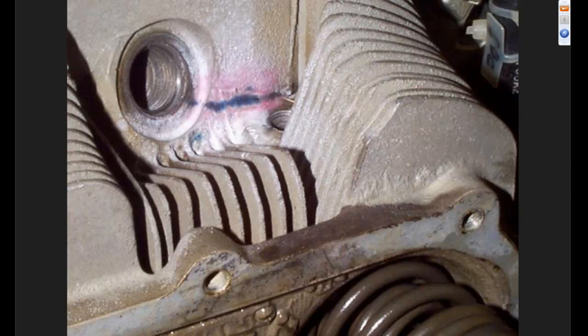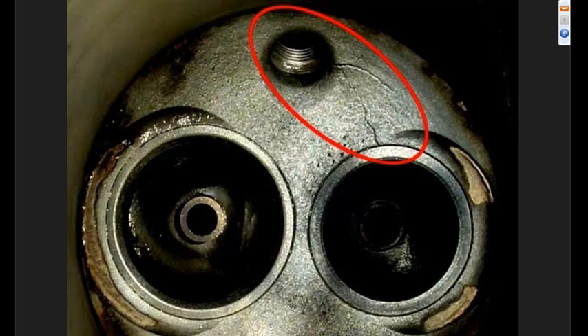And the pink tinge is from where we applied dye penetrant, and the blue line in the crack is actually fuel stains. The fuel filled the crack because the crack extended into the fuel injector hole, and that's what that blue stuff is. But anyway, the head was cracked, and it's a pretty obvious crack because of the blue fuel stain highlighting it. Here's a similar crack on another cylinder that's viewed from the inside of the cylinder. I believe this was a borescope image, and you can see a pretty nasty fatigue crack in the cylinder head emanating from the exhaust valve seat area and growing towards the top spark plug hole.